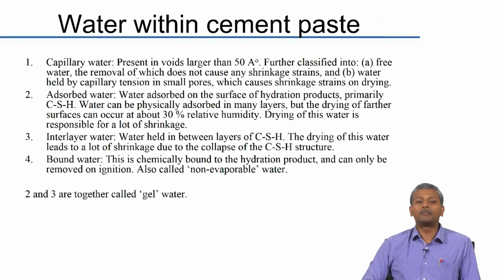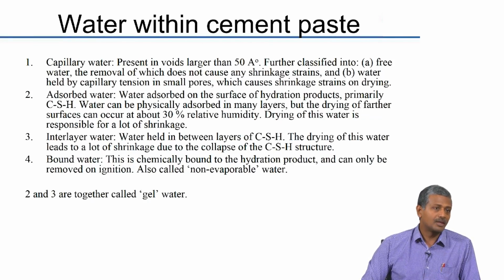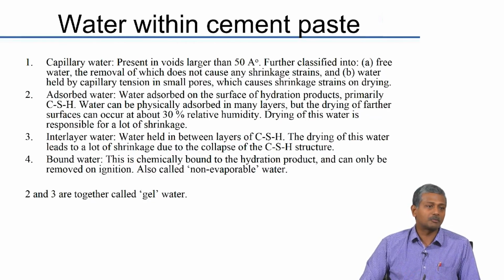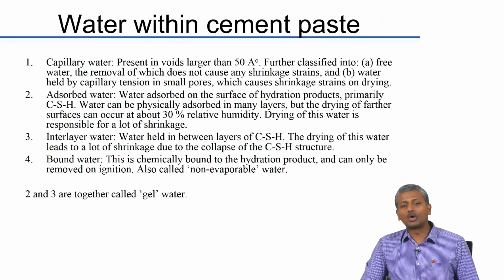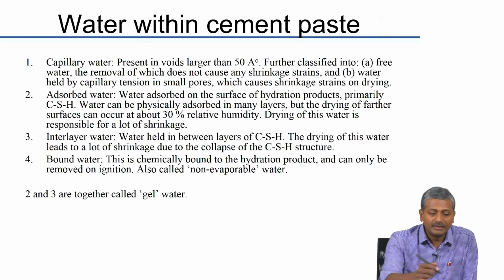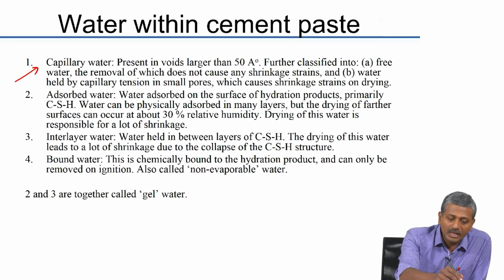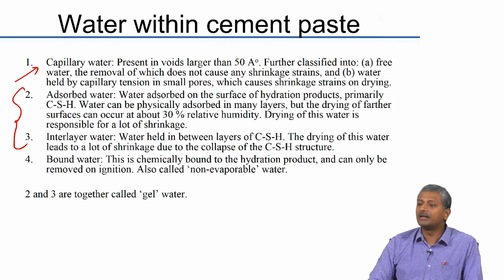Now a very important part of our understanding of the cement paste is our understanding of in what different ways water is held within the cement paste. Because this movement of water within cement is responsible for a lot of issues that are actually noticed with respect to concrete performance. Obviously there is porosity inside the paste, so water is held within the pores. Water which is held within the capillary pores is the capillary water. Water which is held within the gel pores is called gel water and is composed of two types. One is called adsorbed water, the other is called interlayer water.